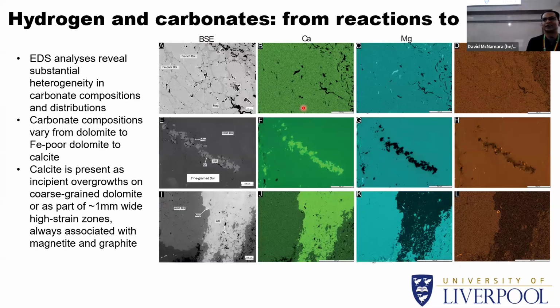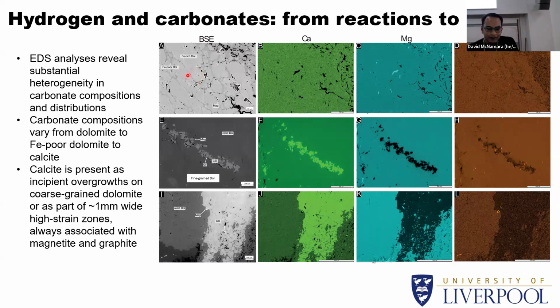If we look at EDS maps of these domains, the darker carbonates in the first row are almost entirely dolomite, but there's a transition from iron-rich dolomite in the core to iron-poor dolomite. There are also bits where we have dolomite with an intervening fringe of calcite, graphite, and magnetite. These domains evolve into wider zones, which have a lot of calcite, graphite, and magnetite, separating domains of relic dolomite. So it's very heterogeneous in terms of carbonate composition.